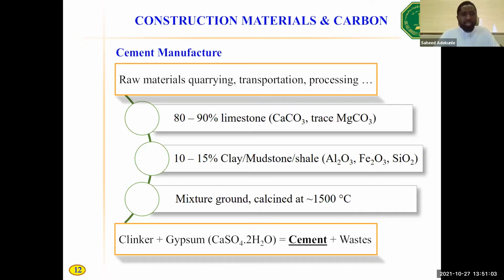Only a minor constituent is the clay, mudstone, or shale. The clay, mudstone, or shale component of cement raw material contributes alumina and ferrite and silica, okay? And this mixture is ground and mixed and sent into the rotary kiln at very high temperature, between 1450 and 1550 Celsius. And then the outcome of the entire thermal treatment is what we call clinker. This clinker, if you intergrind with gypsum, then it becomes what we call cement. Of course, accompanied with some waste products.